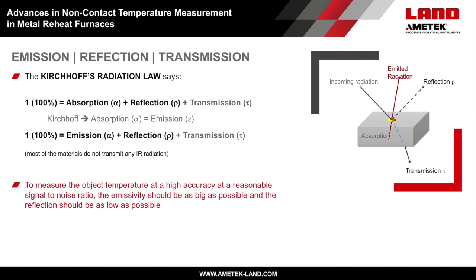Gustav Robert Kirchhoff showed that the sum of all radiation at each time is absorption plus reflection plus transmission of radiation. Further, Kirchhoff showed that the absorption of a material or surface is the same as its emission. This results in an important basic physical law for non-contact temperature measurement. The sum of emission, reflection, and transmission is 100% or 1. In our case, metals usually do not transmit any infrared radiation, so the transmission is zero. For these kinds of materials and surfaces, 1 or 100% is each time emission plus reflection.